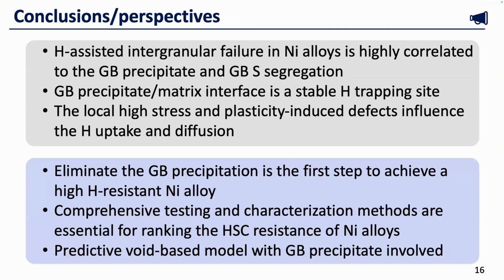So the conclusions and perspectives: hydrogen-assisted intergranular failure in the typically used nickel alloys in the oil and gas industries in Norway is highly correlated to the grain boundary precipitates and grain boundary sulfur segregation. Those interfaces can be stable hydrogen trapping sites, and the local high stress and plasticity-induced effects influence the hydrogen uptake and diffusion. So the future work: eliminating the grain boundary precipitates is the first step to achieve a hydrogen resistant nickel alloy. Nobody knows if this can be achieved, but still promising.